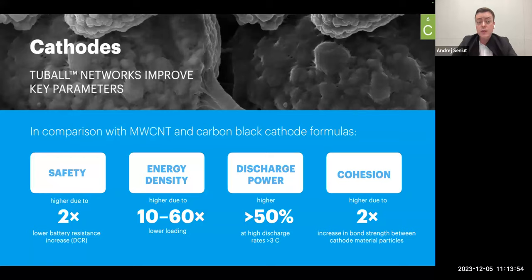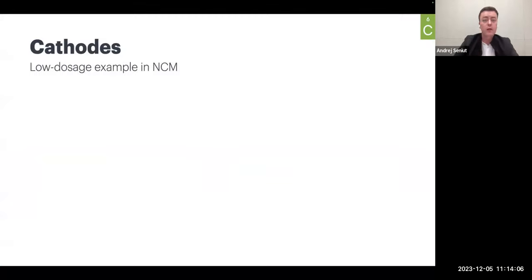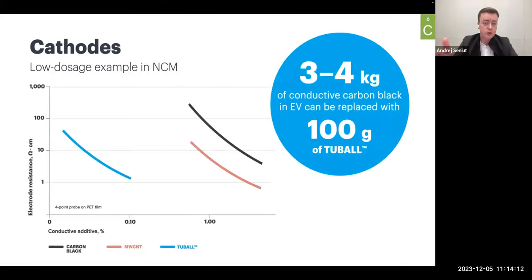And the last one, this is improved cohesion between the particles. Because these networks of single carbon nanotubes, they are long distance and more interparticle, contrary to multiple carbon nanotubes and carbon black. So just some results to illustrate what I have just said. So lower dosage, from 10 to 60 times lower, but another interpretation of this result is that 3 or 4 kgs of conductive carbon black in EV battery pack can be replaced with only 100 grams of TUBALL to achieve the same level of, in this case, electrode resistance on PET film.